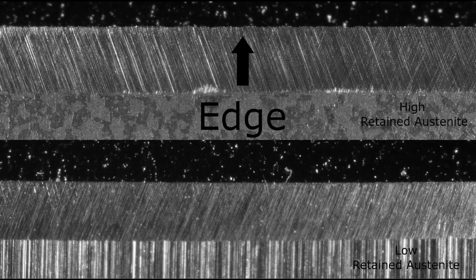So we talked about austenitizing. When you heat the steel up hot, it transforms to a phase called austenite. And when you quench the steel, it transforms to the hard phase of steel, martensite. And if not all of that austenite transforms, some of it is left over or retained. So it's called retained austenite. Retained austenite is soft and it can affect our properties. On a very small microstructure scale, you'll have retained austenite in the steel. And those difficult to sharpen knives, when you would deburr them, would leave behind a ragged edge, which wasn't very sharp.